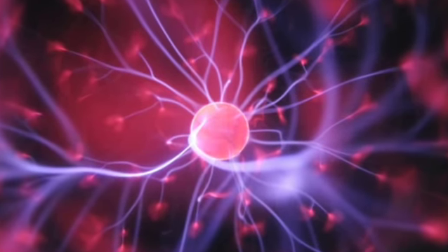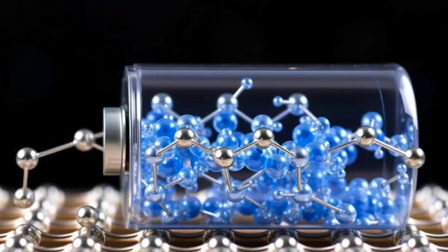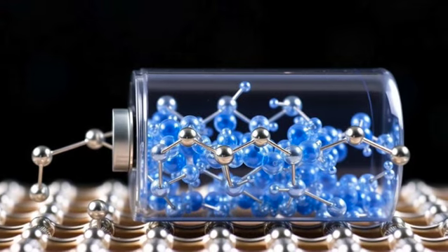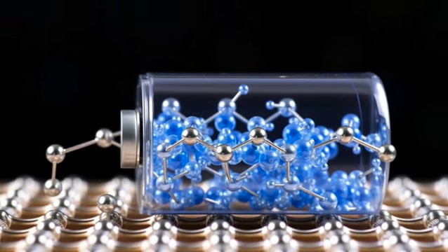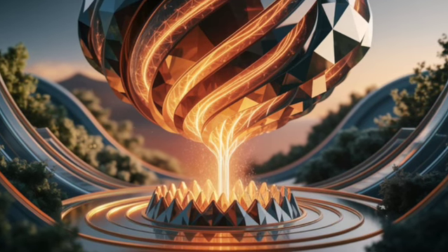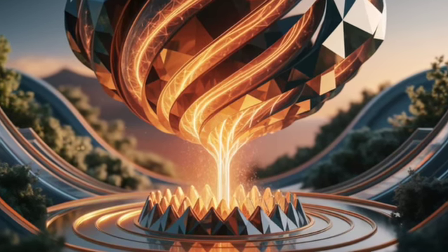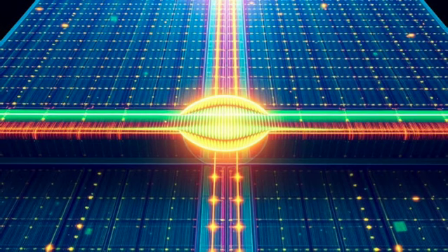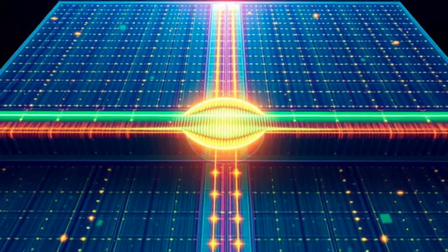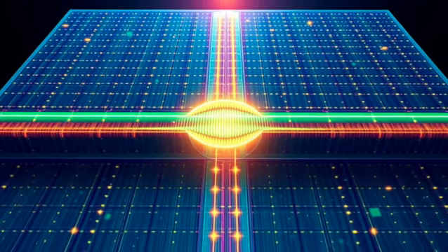The efficiency cascade, where energy is lost along the way. An honest account of the solar fuel process must trace the energy losses that accumulate at each conversion step, because these determine how much solar capacity is needed to deliver a given quantity of final fuel. Starting from 100 units of incident solar energy, a commercial solar panel captures and converts roughly 22 units to electricity, losing the rest as heat and to photons whose energy does not match silicon's absorption band.